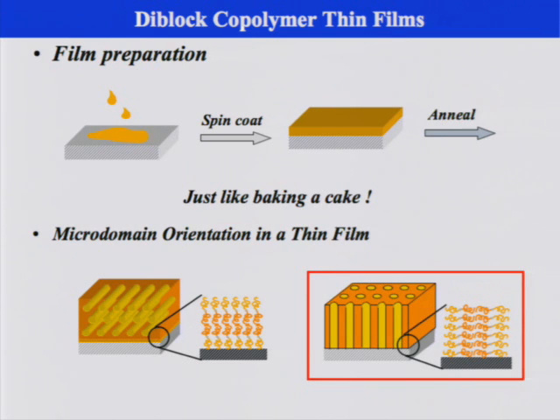And then what you see, using cylinder-forming block copolymer as an example, is that the cylinders either lay parallel to the surface or they can stand normal to the surface.